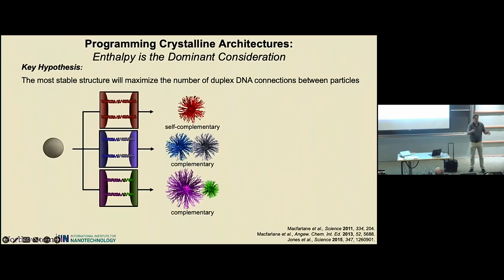And Rob introduced this idea of the complementary contact model. That's just a fancy way of saying that if I have a set of particles, particles will interact with one another to maximize contacts that will lead to hybridization, that will lead to bond formation. It's a bonding argument. It's not rigorously true, but it turns out it works over a large amount, greater than 90% of the design space that at least that we've explored to date.